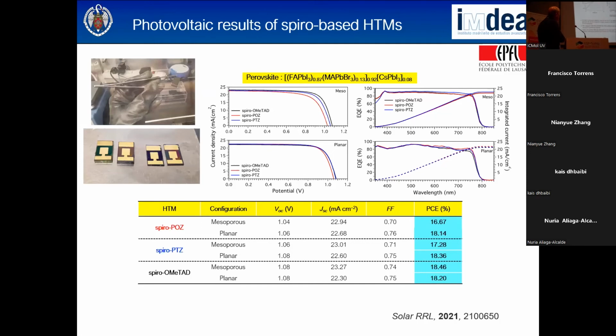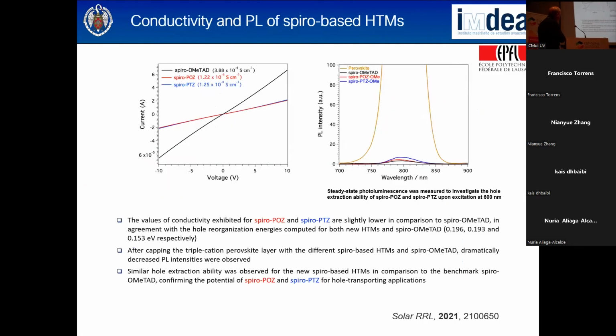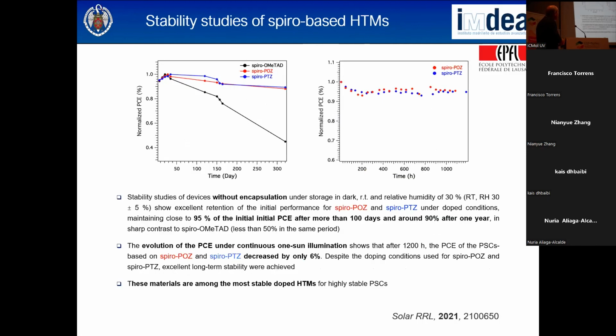The conductivity of the spiro is a little bit higher, around 3 times larger, but they are both around 10 to the minus 4. And this is the quenching of the photoluminescence. This could be considered the efficiency of the molecule to move holes through the molecule. So they are quite similar as well, but pay attention to this, because this is the main difference: stability.